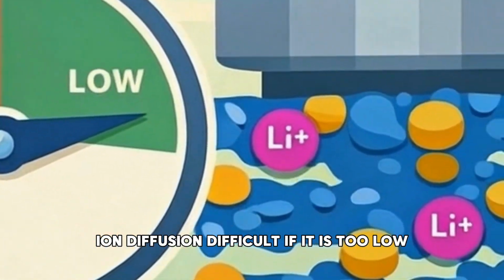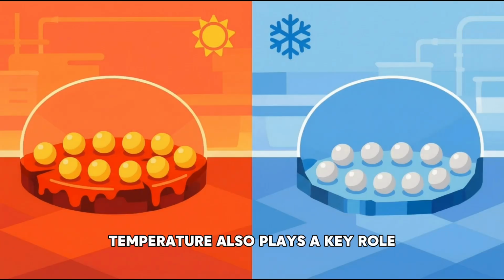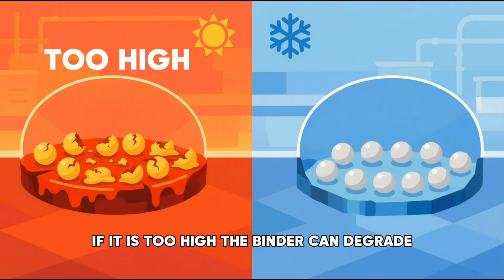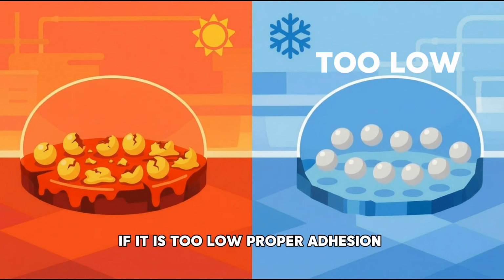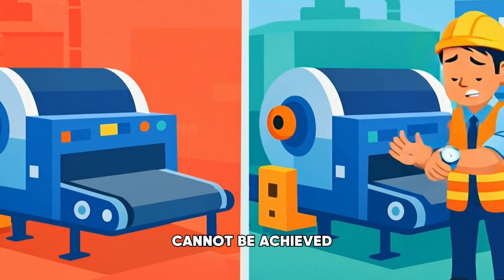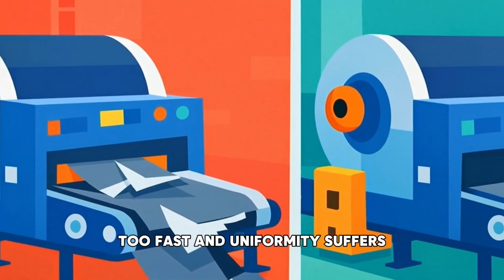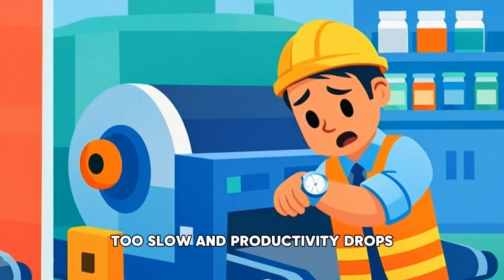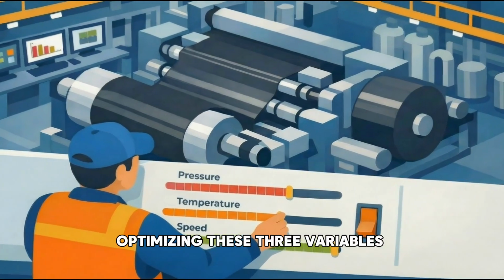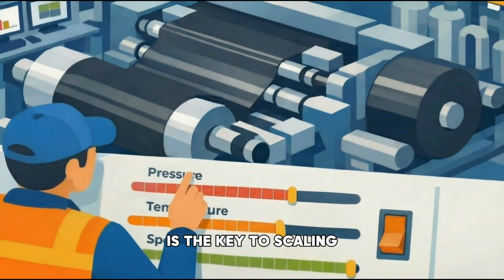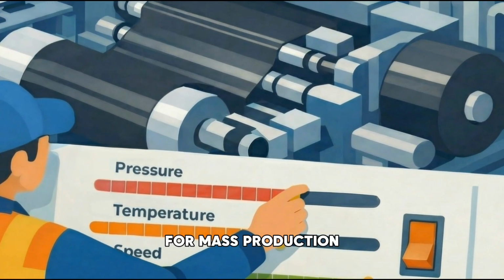If it is too low, adhesion strength weakens. Temperature also plays a key role. If it is too high, the binder can degrade. If it is too low, proper adhesion cannot be achieved. And what about speed? Too fast, and uniformity suffers. Too slow, and productivity drops. Optimizing these three variables is the key to scaling dry electrode manufacturing for mass production.